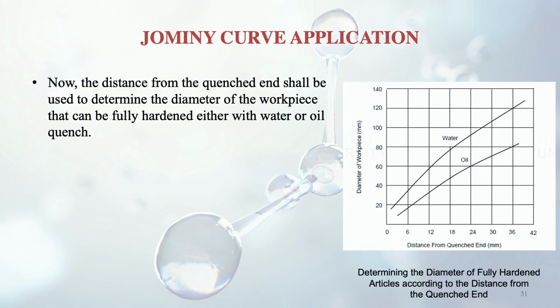So from there we got the distance from the quenched end, and now when we plot it against the diameter of the bar, then we can get the diameter of the cylindrical bar which can be completely hardened with this process. So this is plotted and you can see two graphs here. One is for the water quenching and the other one is for the oil quenching. Now suppose that the distance from the quenched end is about 6 millimeter, as you can see in the graph.